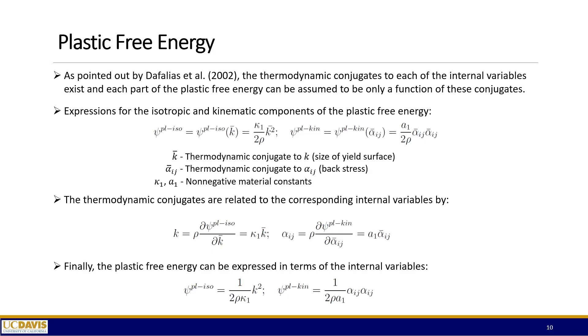Question: for a model with perfect plasticity — no kinematic and no isotropic hardening — does it also have plastic free energy? The answer is no, because the underlying assumption for perfect plasticity is that the material does not evolve at all — there is no evolution of internal variables. Since the physical nature of plastic free energy is that it is related to the evolution of the microstructure, if there is no evolution, then there is no evolution of plastic free energy. So for perfectly plastic material, the plastic free energy does not exist and the actual plastic work equals the dissipation. For kinematic hardening, it must be accounted for, and kinematic hardening is the one that gives proper dissipation.